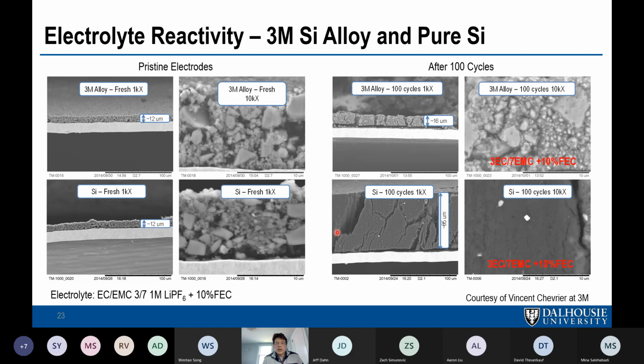The funny thing is the voltage curve hasn't changed. The silicon is still there, it's just disintegrated into very tiny particles, now covered with SEI. The same thing is happening with the alloy also, but at a much slower rate. And that's either because of its composition, or a combination of its composition, I should say, and its lower volume expansion than pure silicon.